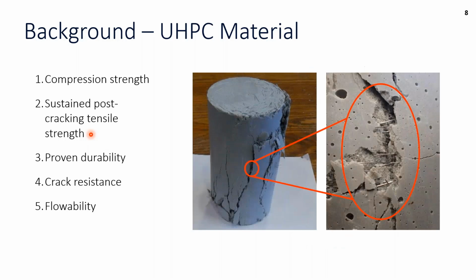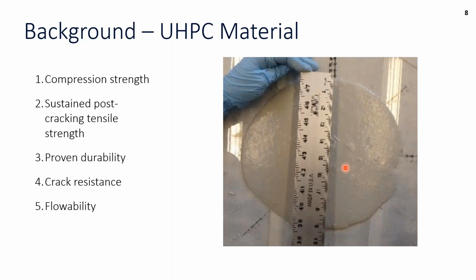This is just a picture of one of those UHPC cylinders, and we have those steel fibers. And that enables us to have no other rebar reinforcement in that cast. It's just the headed shear studs and then the UHPC material. And also, we really rely on that flowability. This allows us to work with more complicated geometries if we have larger skews or we have to use some tighter stud spacing to really be able to just flow around that and make sure that we have an end that's fully protected from future corrosion.